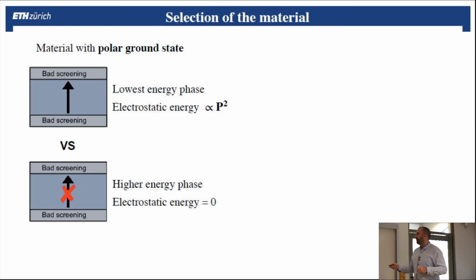So let's go back to our system with this cartoon. So imagine that you have a material that is in the ground state polar. So there is a net polarization, and it is surrounded by a material that doesn't screen well, an insulator, for example. So in that case, the internal energy of this would be the lowest because it's the ground state, but there is an electrostatic energy to pay here due to the discontinuity at the interface. And this energy is proportional to the square of the polarization.